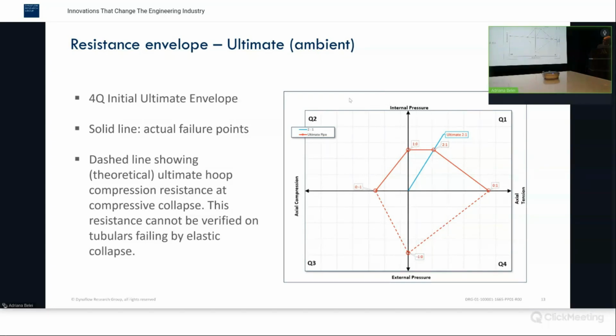So for the external pressure, you see it's a dotted line, and that is based on a calculated theoretical compressive strength. The default well was constructed, or selected, in such a way that elastic collapse was the governing failure mechanism. And for this pipe, it was not possible to create a compressive failure. So that means that it's a theoretical value calculated as indicated in this plot.